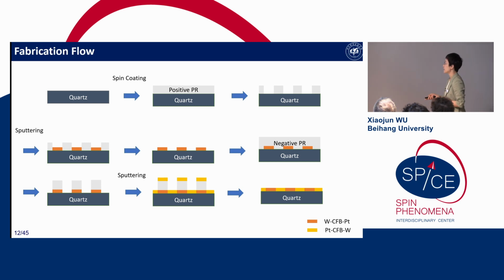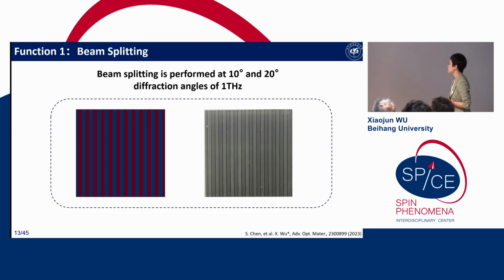So this is the fabrication flow. First we do the spin coating, and then we use the positive PR, and then we etch it, and then we sputter, and then we etch it again, and then we use the negative PR, and etch and sputter. By doing this, we can fabricate this kind of grating pattern. This is the design pattern, and this is the fabricated pattern, just changing the order. One is tungsten, cobalt iron boron, platinum, and the other is platinum, cobalt iron boron, tungsten.